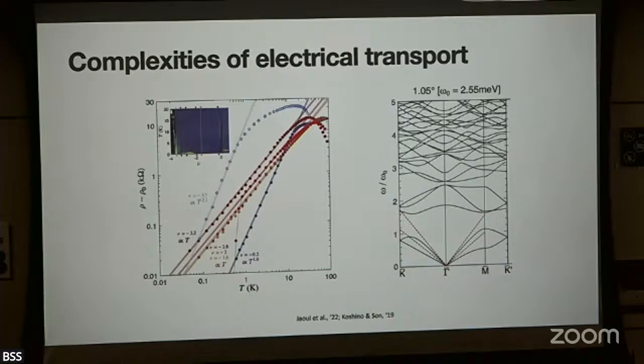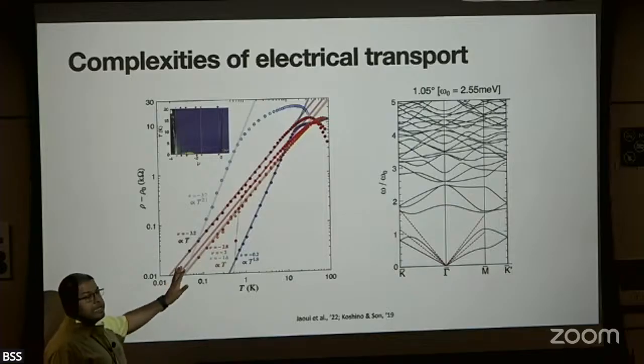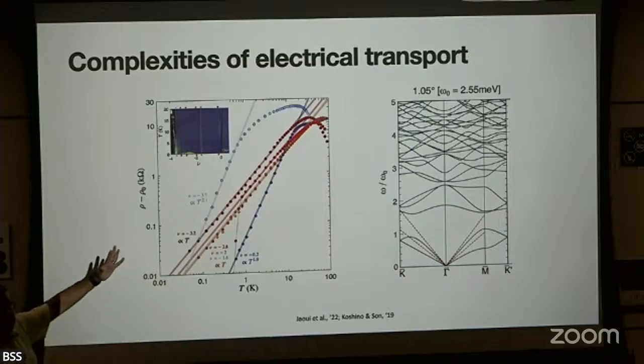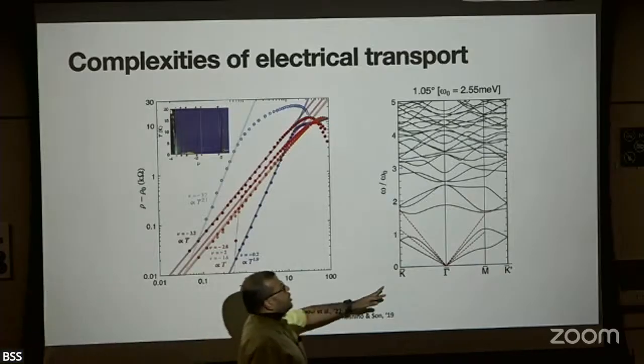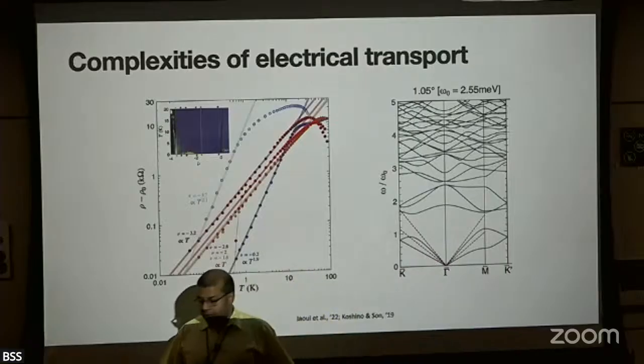Again, there is a particular region in the phase diagram where the linear resistivity that shows up extends over a shocking range of temperature scales, almost from a few tens of milli-K to around 30K without any change in the slope, okay?